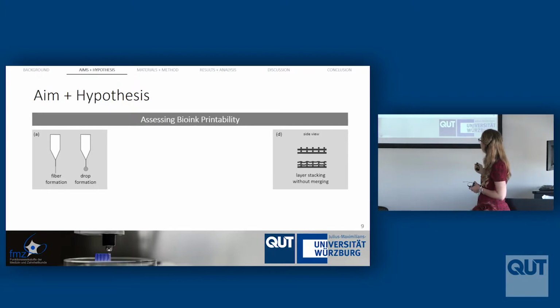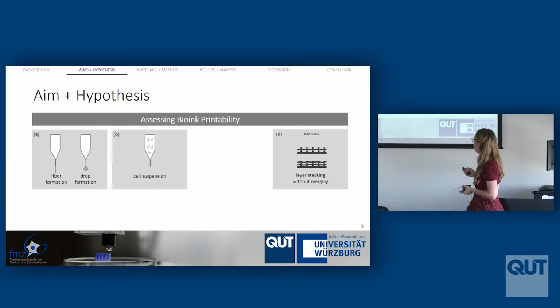And so we can screen for these particular properties really, really easily. It's putting your hydrogel into a syringe with a needle on the bottom and depressing it. And by hand, you're able to tell these two properties very, very quickly and easily. And so you can screen a range of concentrations or different formulations very quickly. But there are two slightly more complex parameters that we want to look at. And the first is cell suspension. So making sure that the hydrogel has the right consistency and viscosity so the cells are suspended in it and so they don't settle down to the bottom, and then the first bit that you print would contain all of the cells and then the rest don't have any more in them anymore. Or that it's not so firm that the cells can't then be extruded.